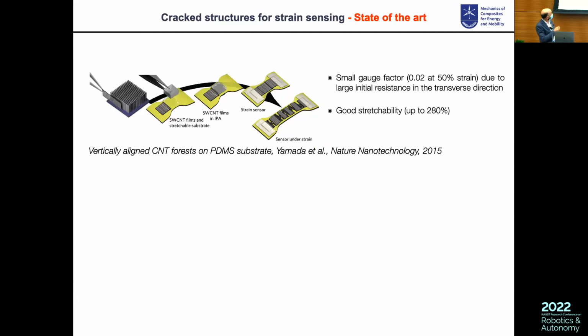So you have this paper in which you take a forest of carbon nanotubes and deposit it on a PDMS substrate, and you pull on this. Here you get a piezoresistivity sensor because you separate the tubes. But of course, you get a small gauge factor because you work in the transverse direction to the nanotube. So you get a conduction, but you get a high resistance at the beginning. So you cannot expect something that will be very piezoresistive.